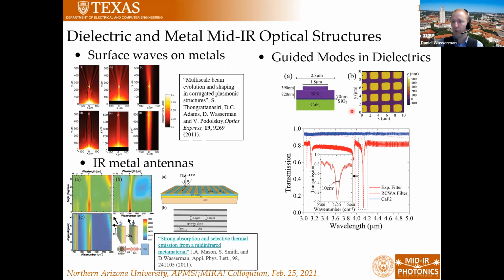Or we can, of course, use dielectric structures. This is a guided mode resonance filter that we designed. It consists of a silicon nitride layer on a calcium fluoride substrate with a periodic square lattice that we patterned into the silicon nitride. And we can couple into these guided modes via the patterned surface. And we can get these really, really strong, narrow filtering modes.